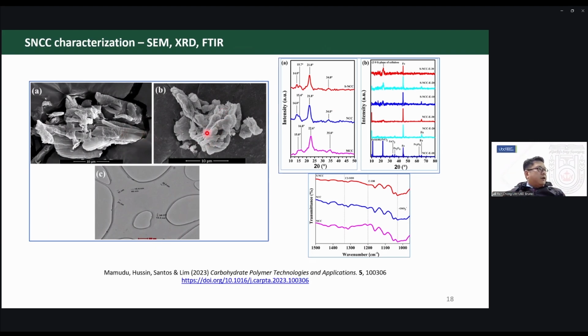Of course, here they look very big because when we did this SEM, the sample was dried, so they agglomerate. But if you look at the TEM, you will see that the size of our SNCC is actually on the order of 40 nanometers, and we also confirmed this later using dynamic light scattering.